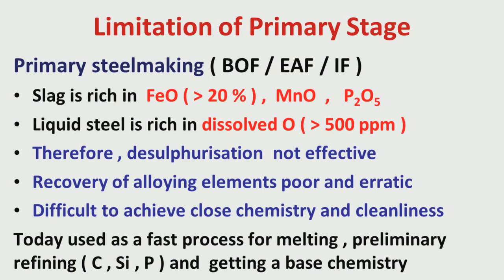because the slag here is very rich. Iron oxide in the slag is more than 20%. There is some amount of MnO, some amount of P2O5, which will create problems during the subsequent stages if this slag is not restricted. Even in the secondary refining stage, if this slag goes, there will be a problem.